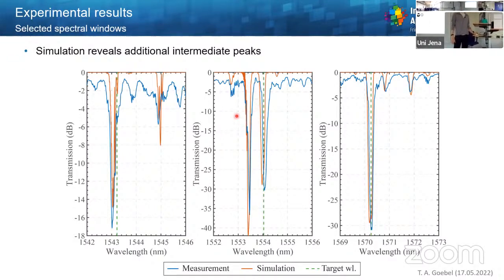Also, another thing that occurred here at 1553.5 nanometer is a resonance which was not intended. This is actually the basic period which we used, the 535 nanometer, and it causes a kind of parasitic resonance. So we use this base period, and then it's modulated to address the resonance pattern. For this initial design with the 10 resonances, this was not taken into account accordingly. But for the next design, we took this one and placed it also on top of one of the resonances so we can utilize it.